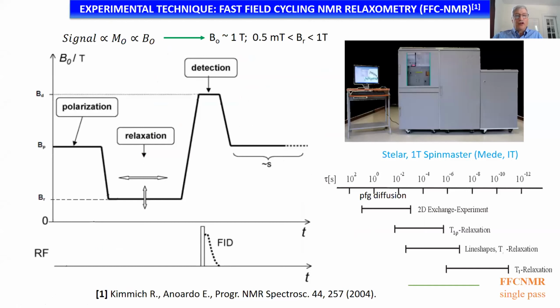We use another technique called fast field cycling magnetic resonance. This is not a standard NMR system. Most NMR is done in a fixed magnetic field, very high field. Here we have the means to vary the field from reasonably high to very low levels. And we watch how the nuclear spins relax back to thermal equilibrium. And we can do that at a very low field. We can vary this field. The net effect being that we can cover 4 or 5 decades of frequency of dynamic range with a single experiment. Usually to cover this range, you have to do a bunch of exotic different NMR experiments. So these are the two techniques we use.